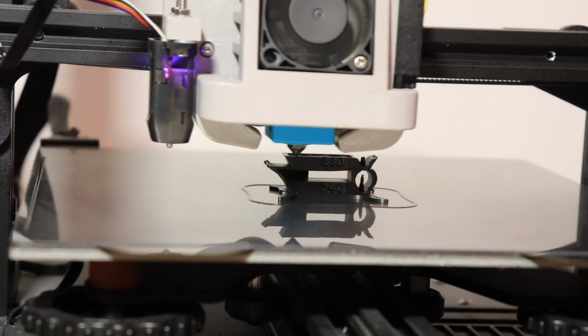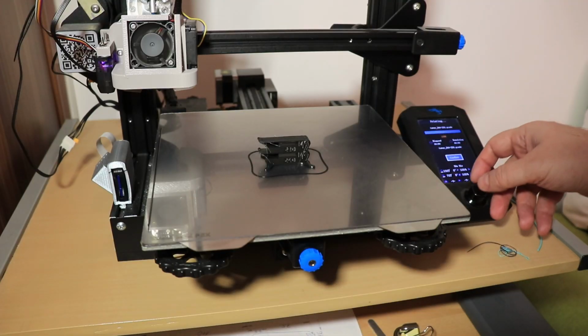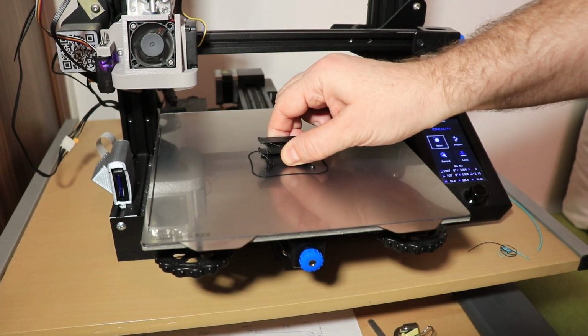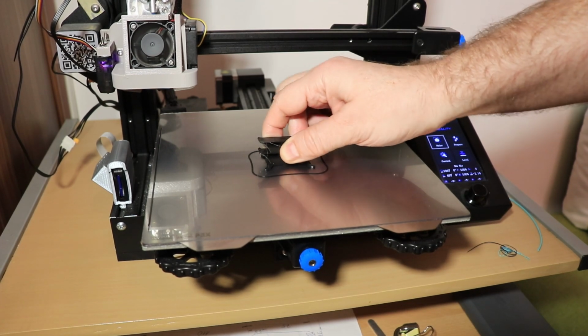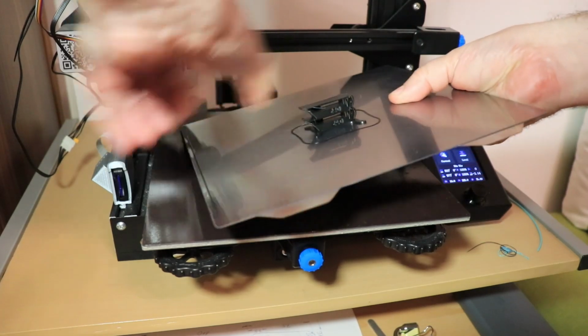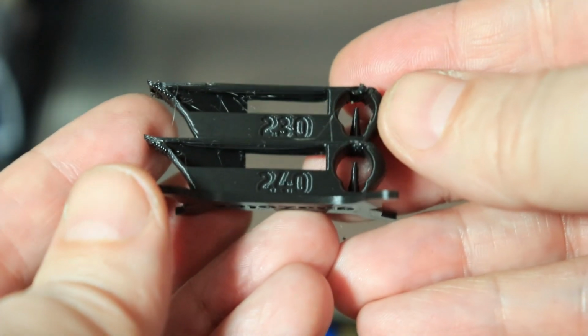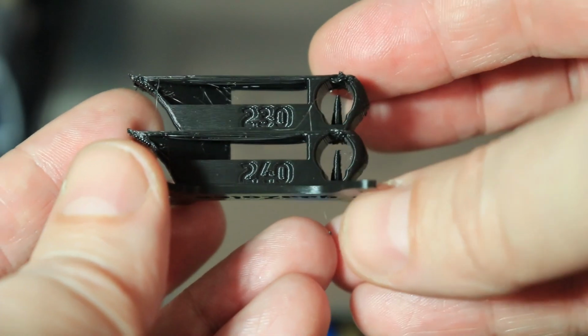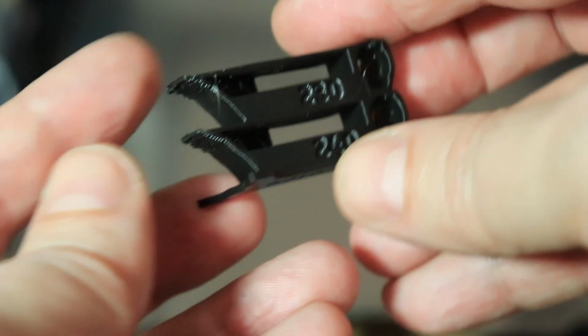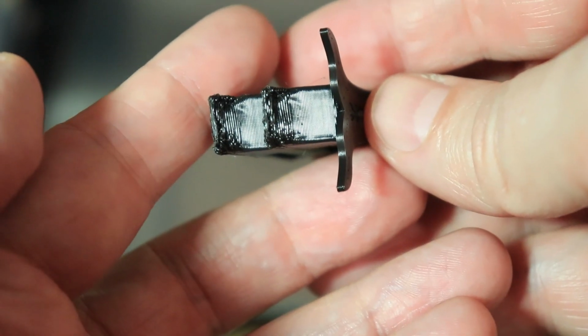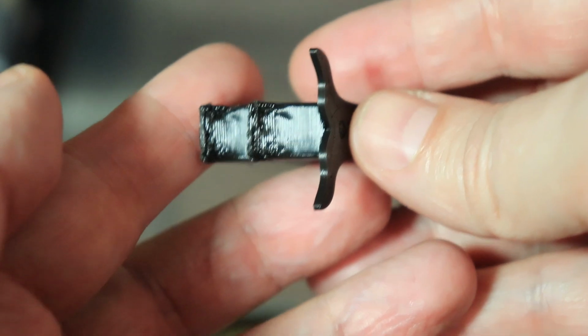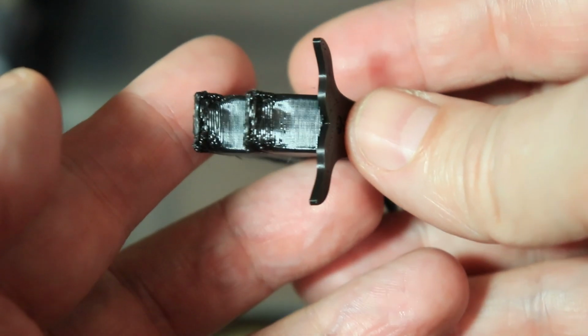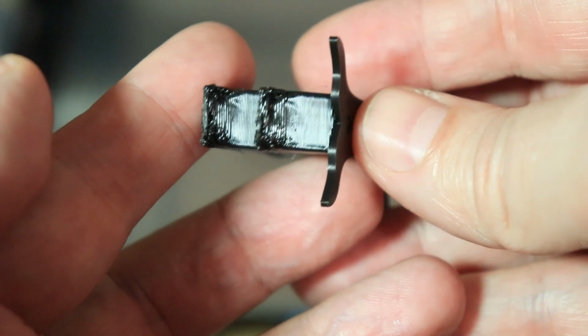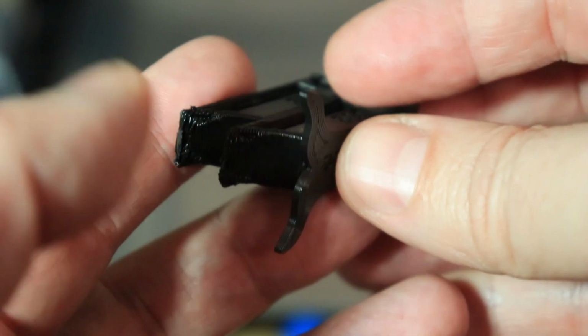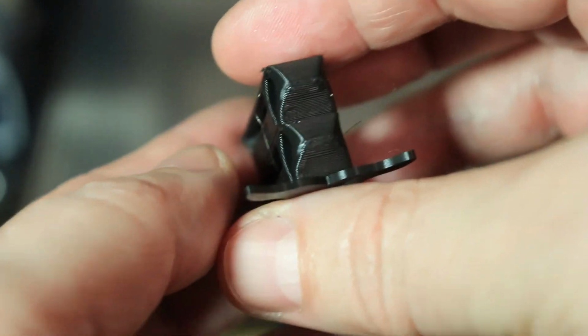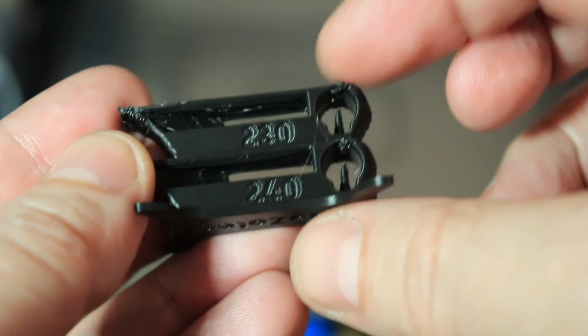The part cooling fan is on 15%. Printing is finished, and before it cools down, I always want to check the bed adhesion immediately, which looks great. Quite a decent temperature tower. The bridging came out great, very minimal stringing I can see. This means the filament is dry. The only problem I can see is that it has some problems on the 60-degree overhang, and the reason for this is the weaker part cooling. I left it at 15%, but it was more than recommended, which is to completely disable the fan. Anyway, I print all test specimens at 235 degrees Celsius.